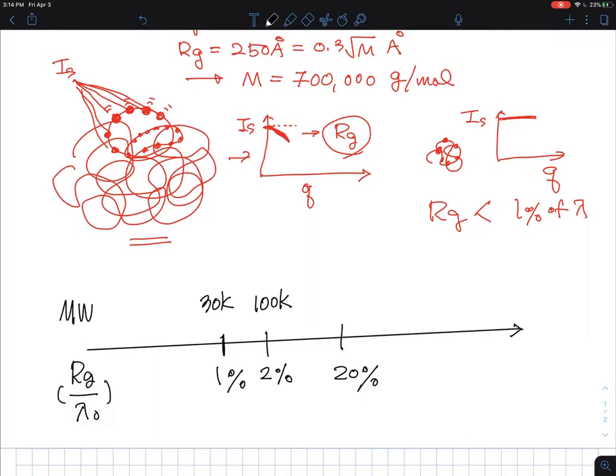If one of your friends says, hey, you have a light scattering equipment, I made a polymer sample, you know, the molecular weight is not so high, but I really want to measure the size of the polymer. GPC says that the weight average molecular weight is, for example, like 30K or 100K. Can I measure the size using the light scattering? You just say no, you can't do that because the size is so small compared to the wavelength of the light, there's not enough reduction as changing the scattering angle. So although you have a super-duper light scattering instrument, you cannot really see the changes.